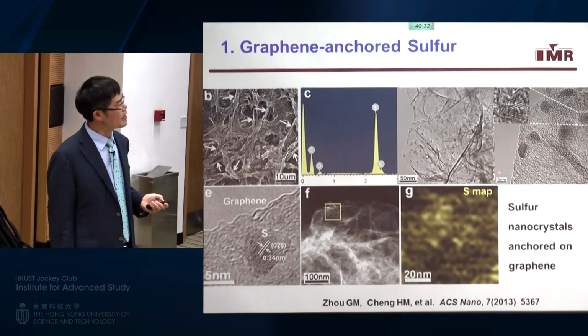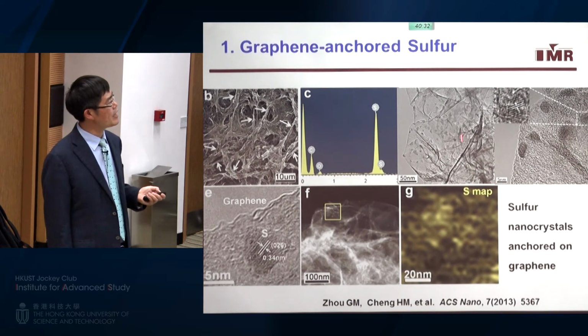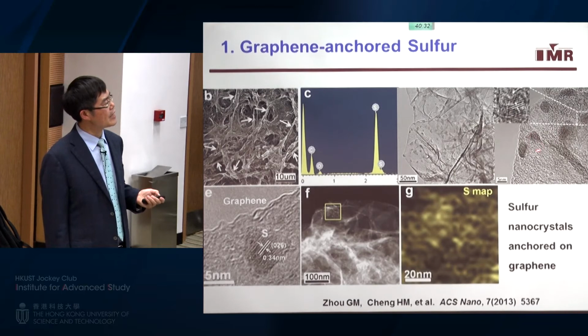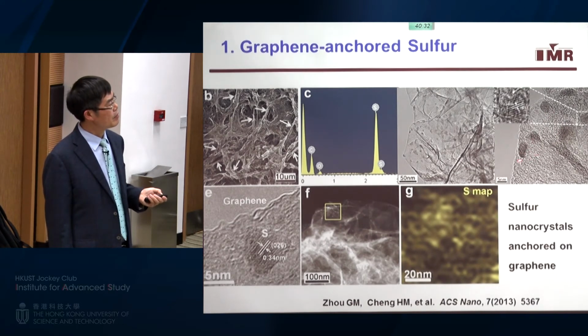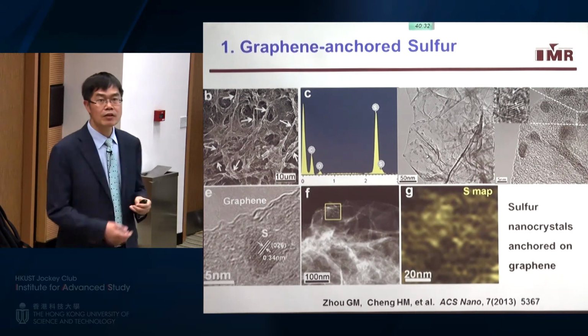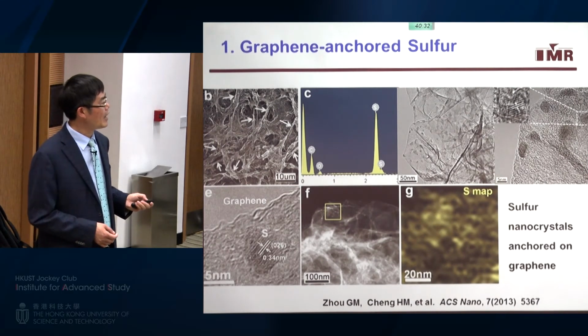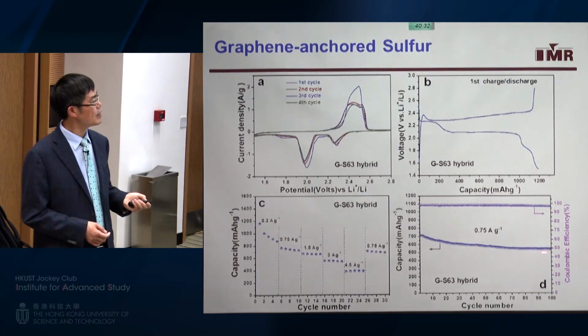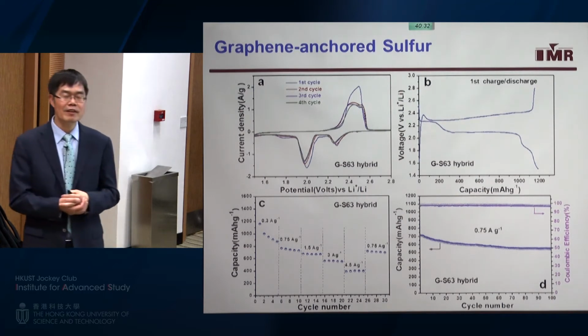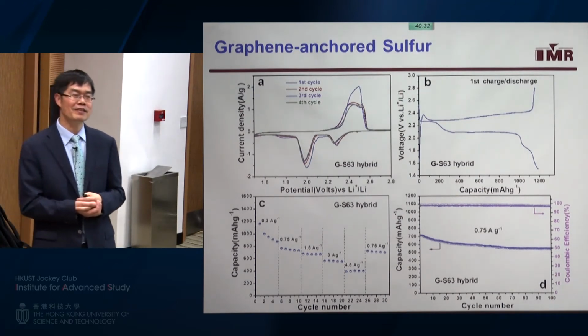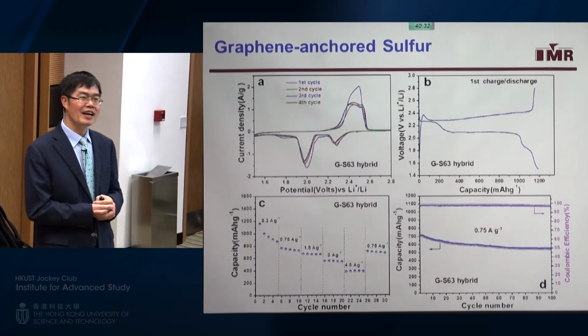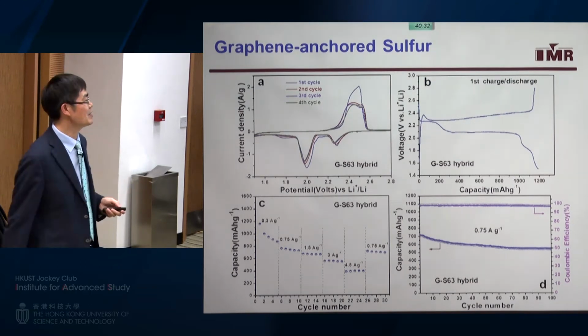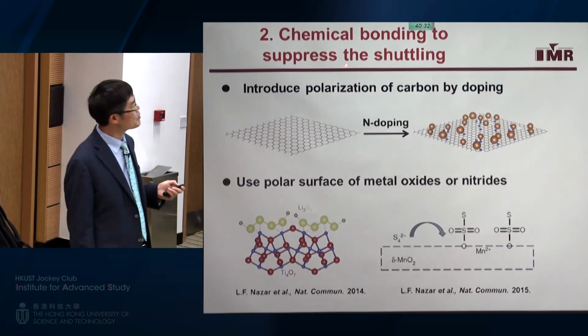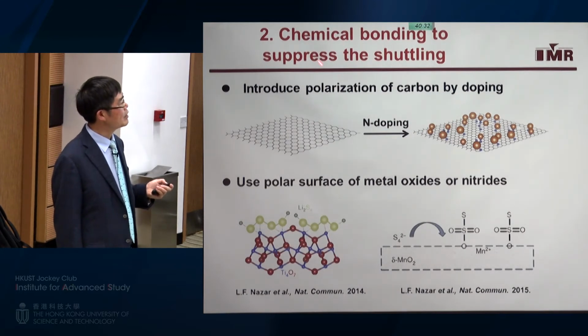So first, we think because graphene is a layered material, we may anchor the sulfur on the network of the graphene or wrap it by the graphene. So we do find sulfur nanocrystals can be wrapped in graphene, and we can improve its performance, as I show you here. But this is our first approach, and we found that it's quite difficult because the process is complicated and the material we can obtain is very limited. So another way is we are also thinking about chemical bonding to suppress this shuttling.